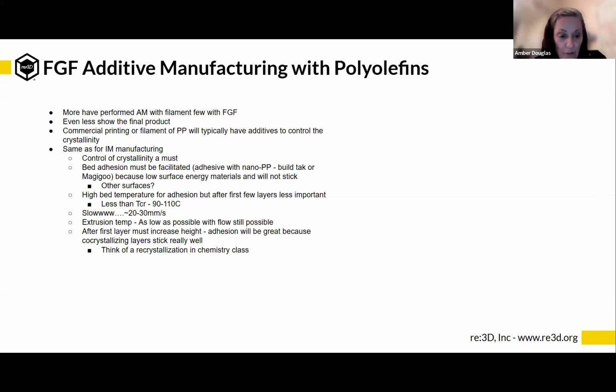And even so slow, it may make you become impatient. About 20 millimeters per second or so. It's pretty slow. But you can control the crystallinity like that and you can get really good prints. And you want to have an enclosure. I put a little heated fan in there. I'm kind of debating not having that in there just because of the airflow.